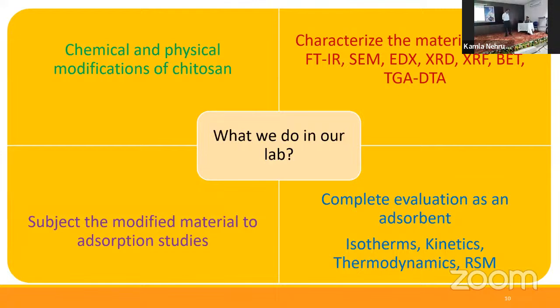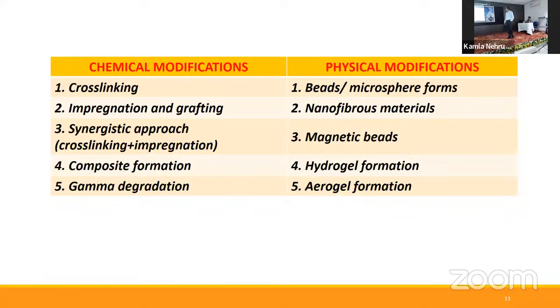What do we do in our lab? We carry out chemical and physical modifications of chitosan, followed by characterization and then application to various adsorption studies, followed by theoretical aspects, including response surface methodology, the RSM modeling study. The chemical modifications which we carry out are cross-linking, impregnation, grafting, combinations of all of them, composite formation, and some gamma degradation also. Physical modifications can be molding the chitosan biopolymer into beads or microspheres, then nanofibers, then magnetic beads, hydrogel formation, and aerogel formation. All these physical modifications are also possible.